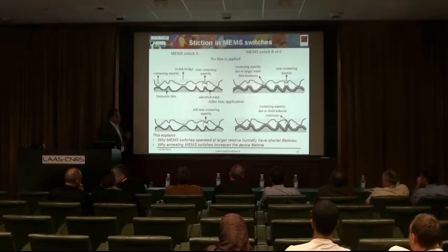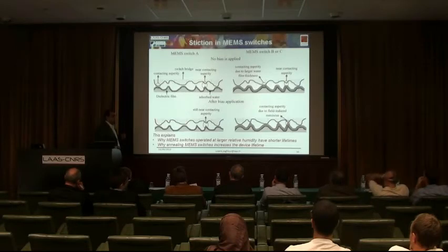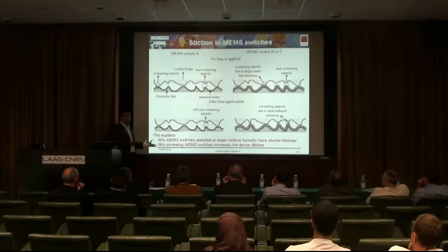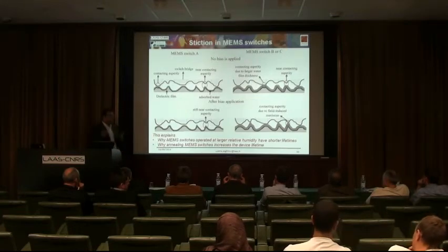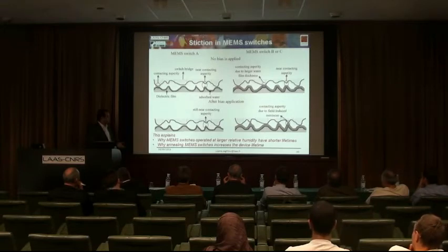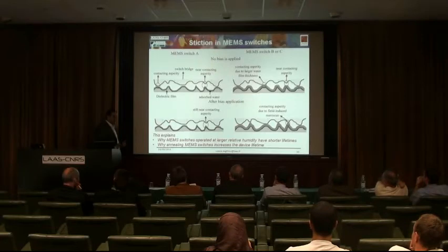This actually explains what we have in the literature, where the lifetime of MEMS switches operated at larger humidity levels is smaller than at smaller humidity levels. People say it is charging. No, it is not the charging. It is the electric field induced meniscus, which is induced by charging, which means you can eliminate it by reducing the humidity level or packaging your device in a dry environment. The other important point here is we understand now why, when we anneal MEMS devices before packaging, the lifetime is increasing. It is not because of the charging.